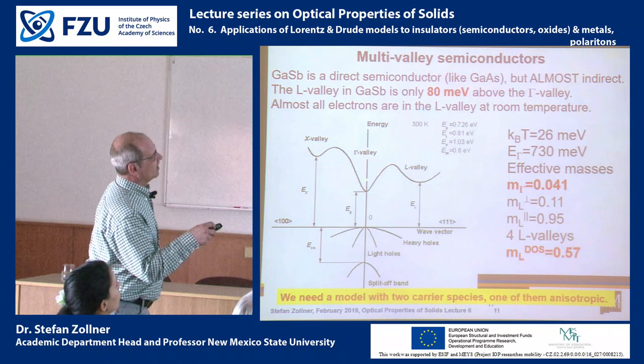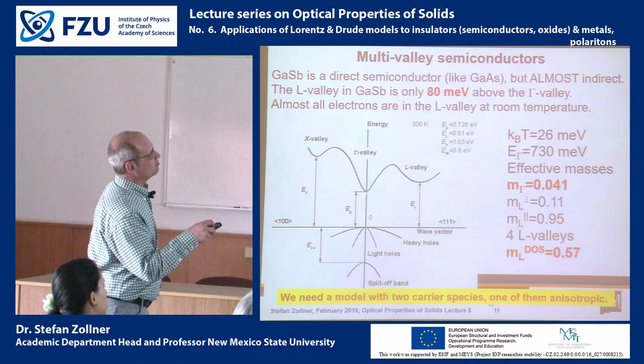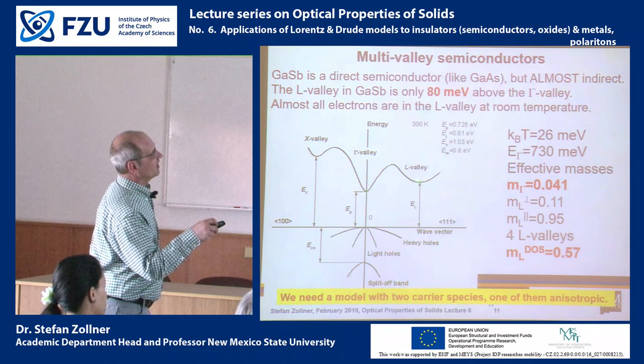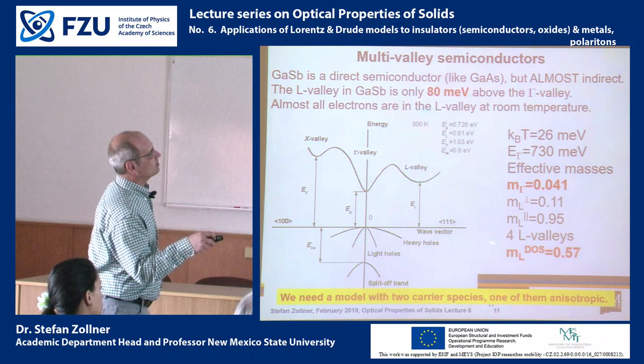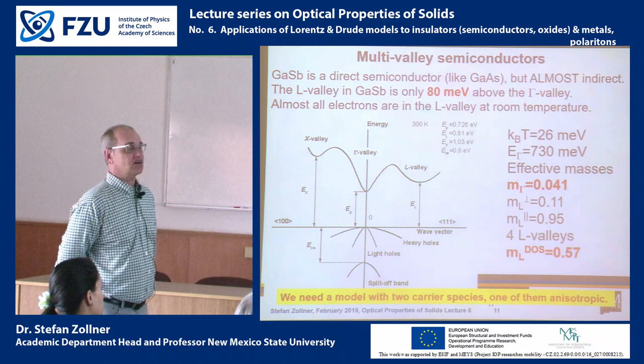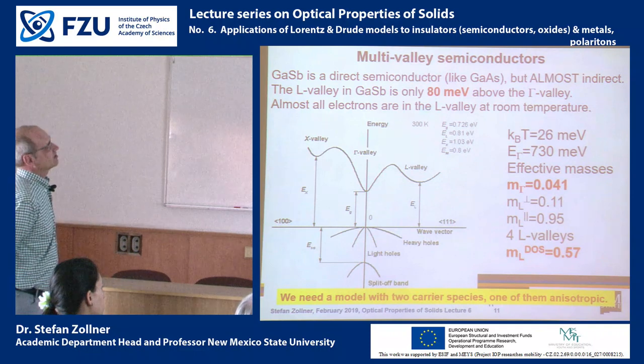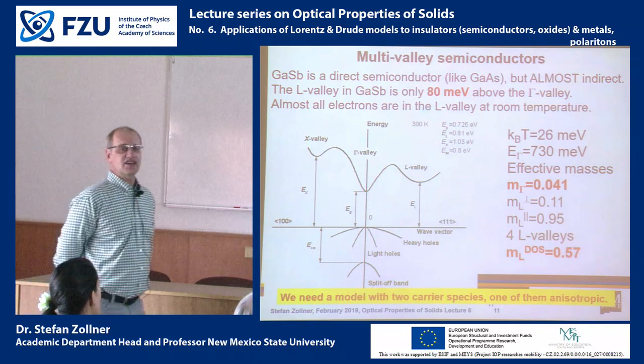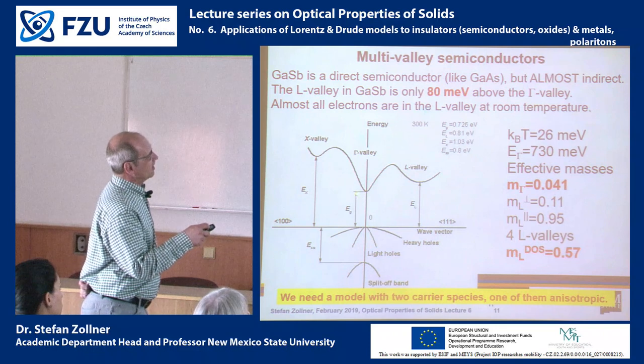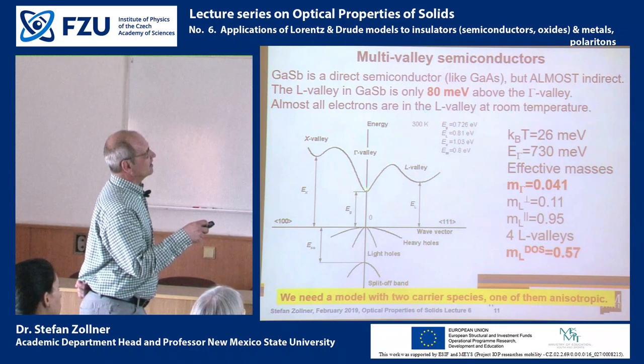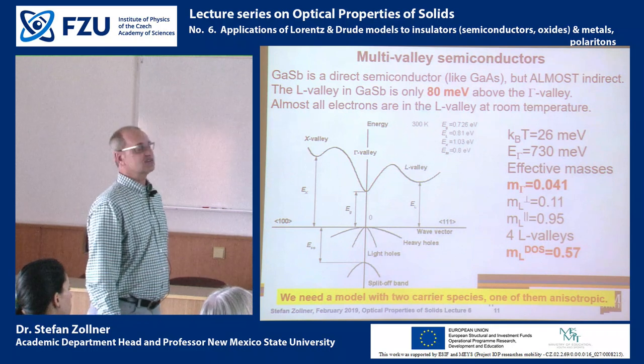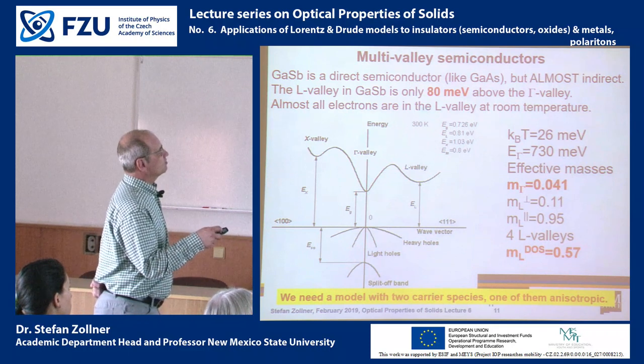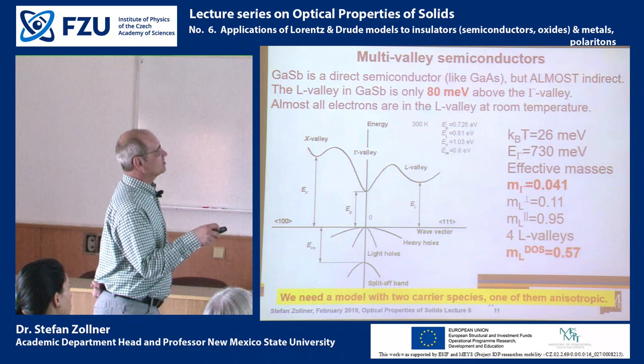So we have the ground state with a mass of 0.041, but just 3 times kT above that, we have an L valley with a more than 10 times larger effective mass. And now you need to do thermodynamics, and you need to calculate how likely is it that an electron is not in the gamma valley, but instead in the L valley. So my student Farzin did that calculation. It's straightforward.